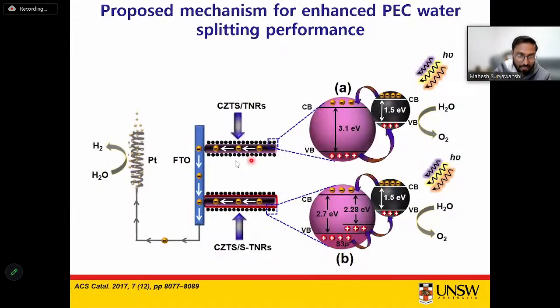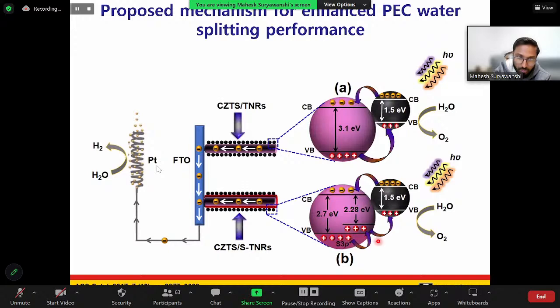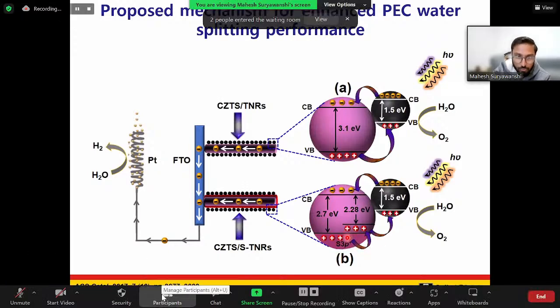So simply, what happens in short: when we sensitize the CZTS on TiO2, you can see there is a type 2 heterostructure formation between TiO2 and the CZTS. In that way, there is an efficient transfer of the electrons generated in the CZTS to the conduction band of the TiO2, and that helps to produce the hydrogen and the oxygen. But when you use the sulfur-doped TiO2 and then sensitize CZTS on it, what happens? As I said earlier, when you dope the sulfur into TiO2, there is a formation of additional energy bands in the TiO2 band energy levels. So that actually helps us to reduce the energy barrier, or the distance required for the hole transfer from the valence band of the TiO2 to the valence band of the CZTS, where the oxygen evolution reaction will happen.